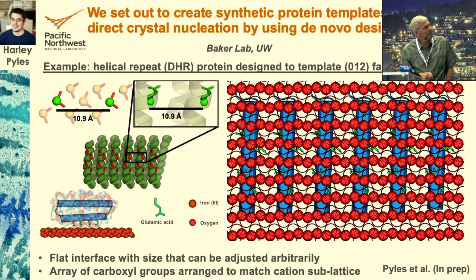And so here's an example of what we did. We're using a motif that Harley decided was probably a good way to go. It's a cross helical structure. So from the side, you can see these two alpha helices. And you can make this an arbitrary length. So it's a repeat protein, so every one of these cross helical bundles is identical. And we've made them from 4 repeats to 34 repeats.